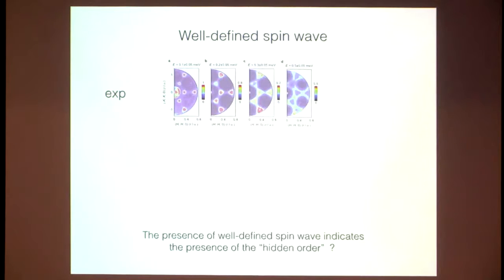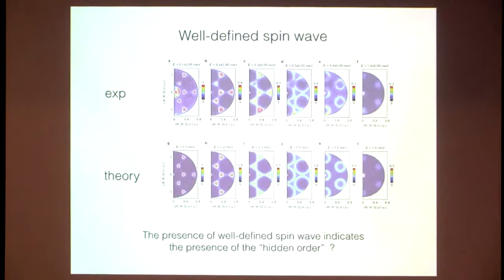This is very low energy. You see this contour is the bottom of the band. And then gradually increase the energy. The contour expands. And this is theory. So that means the system has a well-defined spin wave-like excitation with respect to the ground state.